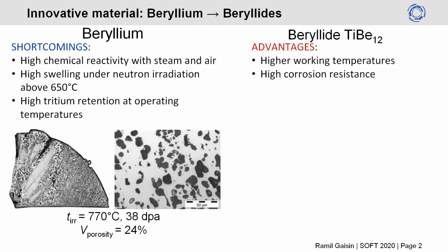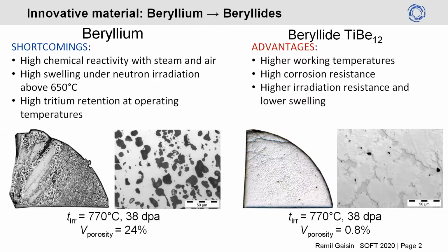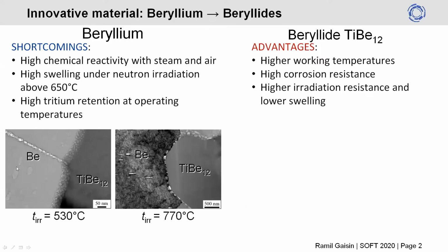This intermetallic compound called titanium beryllide has much higher operating temperatures due to better corrosion resistance and due to much less swelling. Under the same irradiation conditions, beryllium looks like Swiss cheese on the left and beryllide has almost no porosity on the right. Looking much closer to the material with TEM, we always see large hexagonal bubbles in beryllium and very small ones in beryllide.